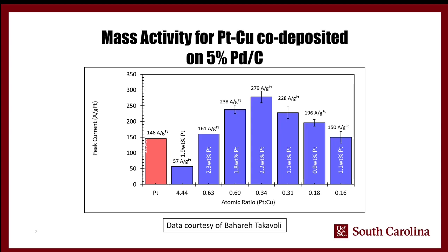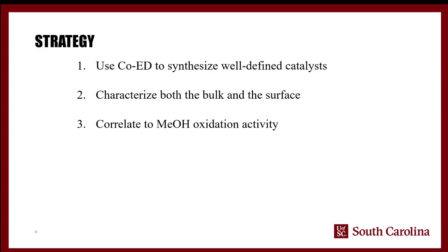utility is greatly increased. So the strategy here is to use this co-electroless deposition method to synthesize well-defined catalysts. We want to try and characterize both the bulk particles and the surface of the particles. The reason we need to do this is, if you characterize the bulk of the particles, you're assuming that they're the same throughout the entire particle, and that's not necessarily true. It is possible to see segregation of atoms to the surface. Sometimes that's a desired thing, sometimes it's not, but it's important to know what's actually happening. And so then, based on that characterization, we'll measure the methanol oxidation activity, and we want to try and correlate the physical characteristics to the activity that we observe, and try and figure out where the optimal ratios are for these different platinum metal bimetallic particles.